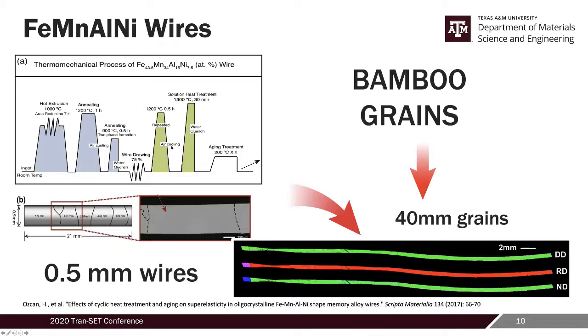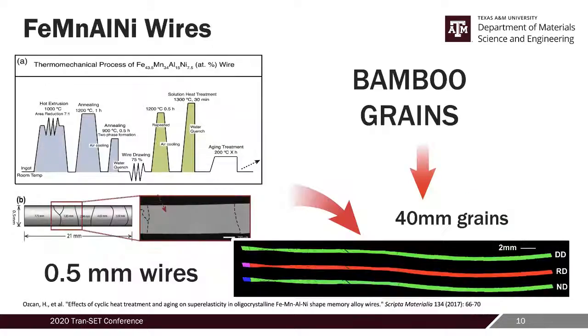After that, you need to solution heat treat your material, and to strengthen your material, you need to do aging heat treatments. We did, in this case, 200 degrees C for different amounts of time. And after that grain growth, we were able to increase the grain size up to 40 millimeters in 0.5 millimeter wires. However, before I talk about the larger diameters, of course, this wire is very small for civil engineering applications.